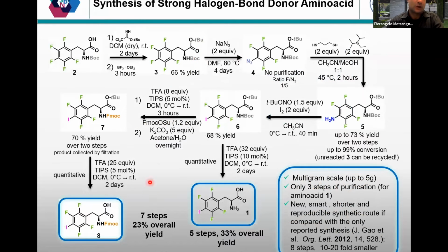But we were not happy with that. We wanted to have clearer evidence. Therefore, we synthesized this peptide, which is now tetrafluorinated. And now this halogen bond donor is much stronger. But synthesizing this molecule was a nightmare. It took 1 year, 5 different people, and only one lady, Luisa Lasciarfari, was able to synthesize this, and now we have scaled this up to 5 grams in one single batch.